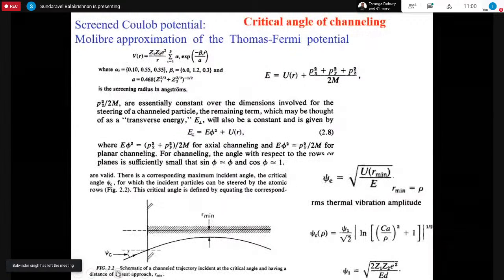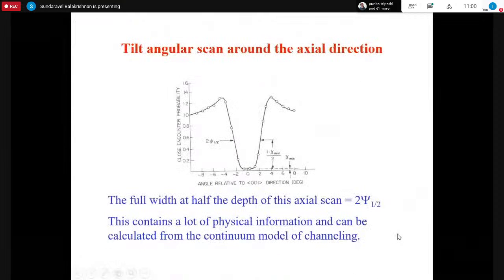And this angle psi c, the critical angle of channeling, is given by the square root of U(r minimum) divided by the energy. This r minimum is the distance between the string and the incident ion at the time of that collision. So it is the potential at r minimum divided by the energy. And this psi c we can measure experimentally, and it is given by this expression.